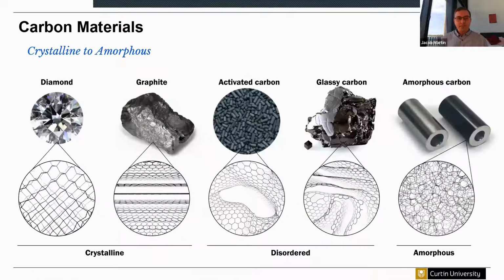So just starting off, one of the topics that we're very interested in is what's the nanostructure of disordered carbon? So putting this along the scale, you've got the crystalline forms of carbon, diamond and graphite. And then you've got the amorphous forms of carbon, which have no long-range or short-range order. But the disordered carbons lie in between those two. They have some short-range order, but they don't have any long-range order. And these are very tough to understand. These have been a persistent problem in carbon science for the last sort of 50, 60 years.